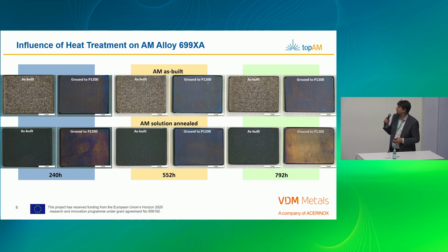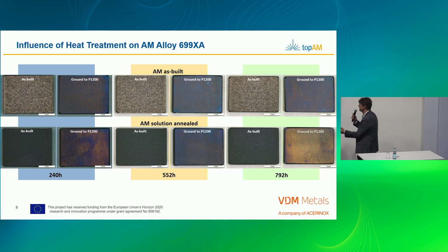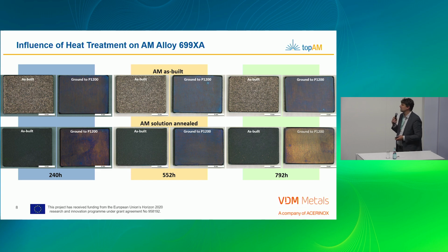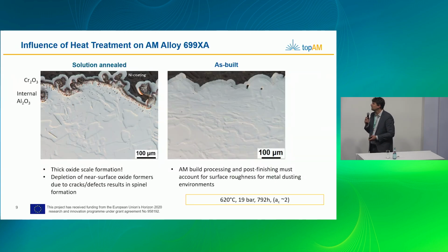And when you look at those, the top is the as-built, on the bottom, solution annealed after the different temperatures. You can see it here on the surface already. And on the as-built ones, we start to find some small graphite. Also, it's not severe. The alloy itself is quite resistant, as I said, but we start to find the evidence of attack, while for the ground material, this is not the case.